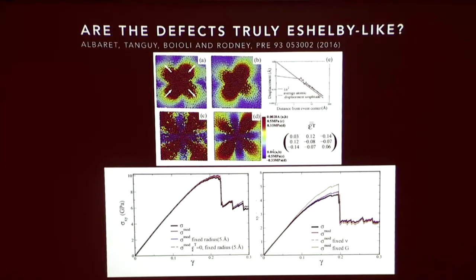So basically what they're doing is shearing the material, looking to see when rearrangements happen. They then use the elastic signature, the Green's function associated with one of these plastic inclusions, to analyze what STZ just happened, how big is it, where is it. From that they infer how much deformation should have happened at the boundary and how the stress should have dropped. So they're getting the STZs out of direct observation of the simulation, and from that information trying to reproduce the stress-strain curve.